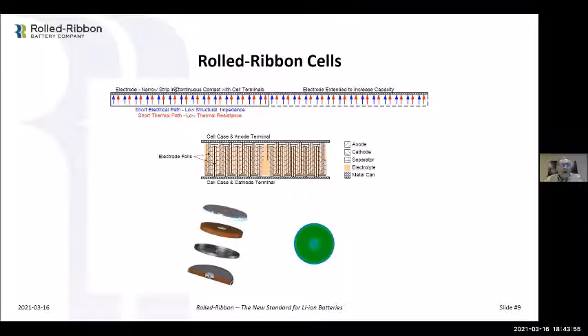Now, if you want a higher capacity roll ribbon cell, you need more electrode, just like everybody does, more square inches. So what happens is you have a longer ribbon, just like you did with the wound cell. But the difference is we don't have the tab at the end. As we extend the ribbon length, we're extending effectively more tab because we are continuously tabbed along the entire edge of the electrode here. And so as you're adding more electrode, you're adding more surface area to get current and to get thermal energy out of the cell so you can draw the heat out.